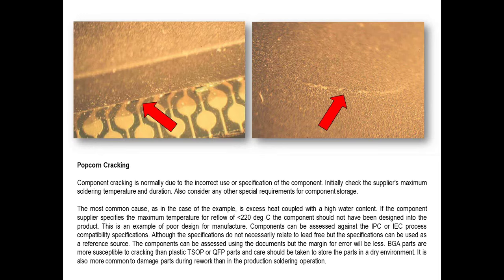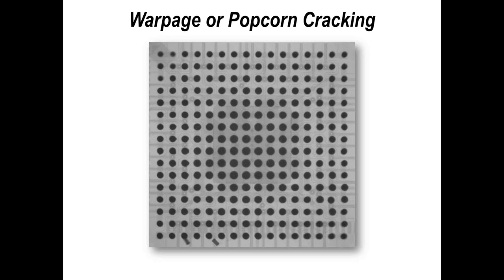Now, one of the nice things, if you're using X-ray, you can see the degree of this, or you can actually see, perhaps not a failure, but you can actually see how the package warps during the reflow process. Now, what I've done here is just taken a photograph of a board that I've created specifically to use on our X-ray machine at Productronica. And what we've got here is a nice example of warpage. And if you look closely, I think most of you that are familiar with X-ray inspection will be able to see that the balls are a different size.